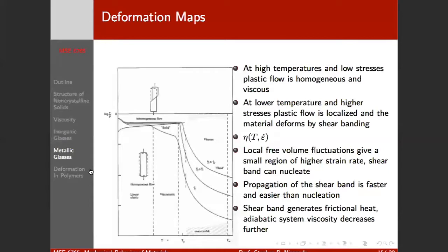So metallic glasses can be conducted very fast, right? Yes, but still, the conduction is not nearly as fast as... right? You're hitting on a controversial area. Okay, so Professor Lewandowski from Case has a couple classic papers where he measured the temperature rise in the shear band and basically said it's a case of adiabatic heating, and the temperature in the shear band went up to approximately the melting temperature, some very high homologous temperature.